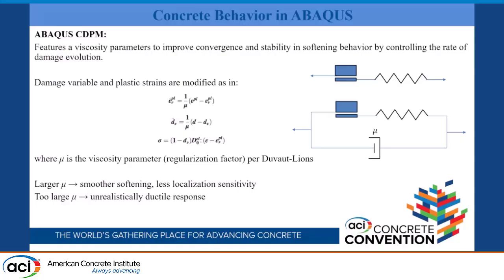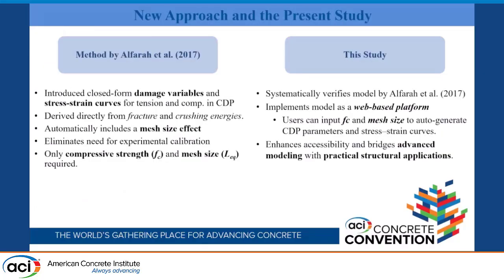But how much of this force, how would you determine it? It's unclear. That's what's giving my colleagues a problem. What should we set the value of this parameter mu that controls it? If you use too large a mu, you're adding too much fictitious force and strength to your system. Not really strength, because if you waited long enough, presumably this will converge, but this is viscosity for you. And if you're using too little, you still have the mesh dependency.